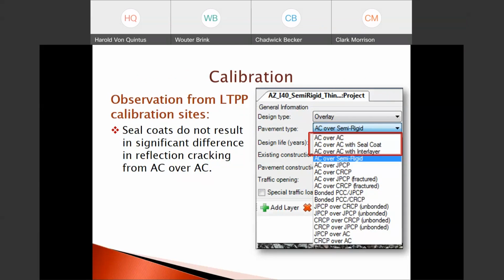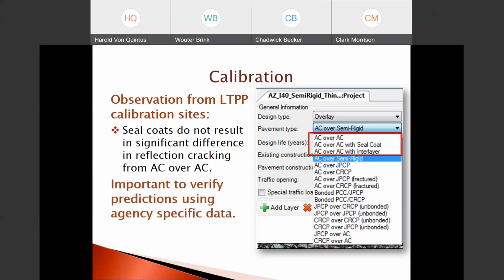The reason for that we'll get into a little later, but for the majority of the sites, on average, the seal coats and the interlayers made little impact on the predicted fatigue as well as transverse cracks on these sections that were used for calibration.